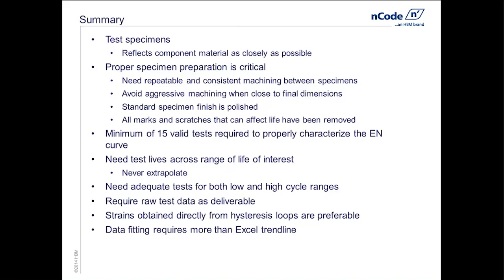A simple regression using a trend line inside of Excel reverses the independent and dependent variables. The independent variable is the y-axis in our test, whereas in a standard regression it's the x. And so the regression is a little more complex than just doing a simple Excel calculation using a trendline.